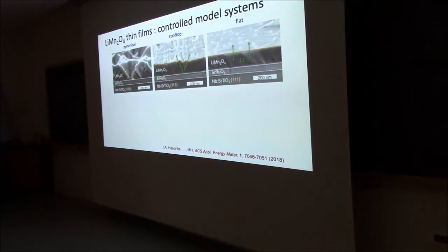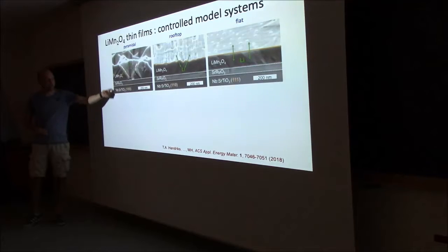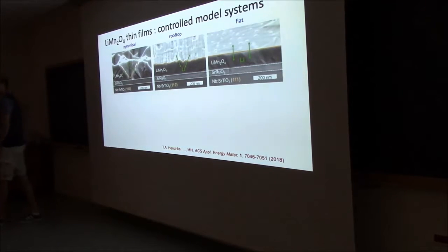So with lithium manganese oxide, it's a spinel material. You take strontium titanate as a substrate, as we all do as a starting point, although I tell my students, if you don't need to, don't do that. Terrible substrate. But it's a spinel, so the spinel fits reasonably well on a perovskite. But what you see happening here, you take the 100 orientation and you grow a spinel. Spinel is about twice as big. The A and the B direction are nicely aligned with the A and B of the substrate. With the out-of-plane direction, the C is then pointing out.